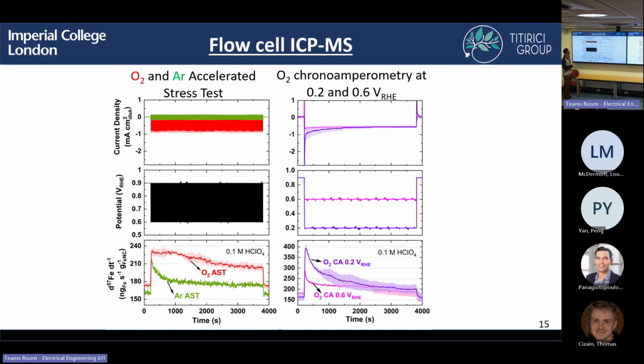And then if you look at the chronoamperometry, so this is holding the potential during the 1 hour measurement, we see that as we step the potential from 0.9 to 0.2 volts, we have a really significant spike in the iron dissolution, whereas when we go from 0.9 to 0.6, we have a spike, but to a lesser degree. And we see from the current that we still end up with around the same current density, again limited by the solubility of oxygen.